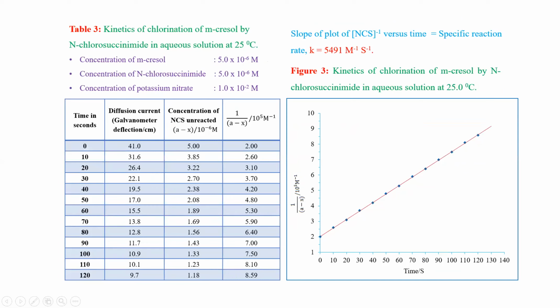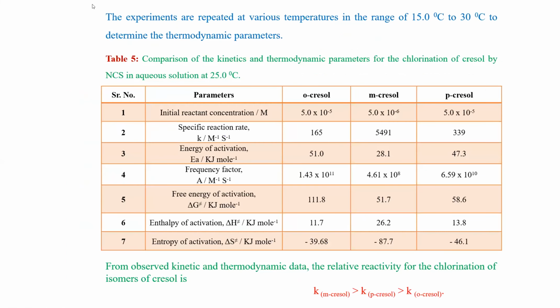So after the three experimental setups, these experiments are repeated at various temperatures ranging from 15 to 30 degrees Celsius. We determine the thermodynamic parameters. Some thermodynamic parameters are shown here, calculated by this reaction. The initial concentration is also shown in the given table. Then the specific reaction rate I also told and showed already.